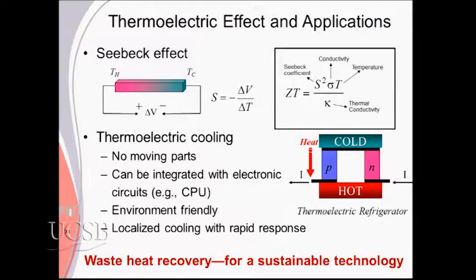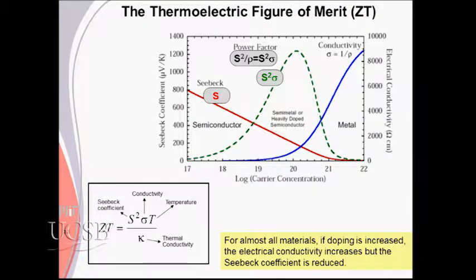That sounds so wonderful. So the problem has been hard, and the reason is that it isn't easy to make this factor ZT, this figure of merit, greater than 1. Why? This Seebeck coefficient is a sort of intrinsic property of a material, but it depends on the carrier concentration. Here's carrier concentration, it's a log plot. And you can see as carriers increase, the Seebeck coefficient goes down. Okay, that's the law of nature. But we want that to be large.